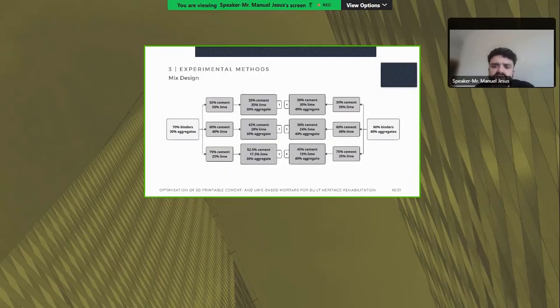Regarding the mix design, initially we defined two primary mortar formulations based on different binder to aggregate ratios. The first one had 70% of binders and 30% of aggregates, and the second one had 60% of binders and 40% of aggregates. For each ratio, we tested 3 different binder combinations, resulting in 6 base formulations without superplasticizers. So from this first set of trials, the best compositions were selected for an optimization using superplasticizers.